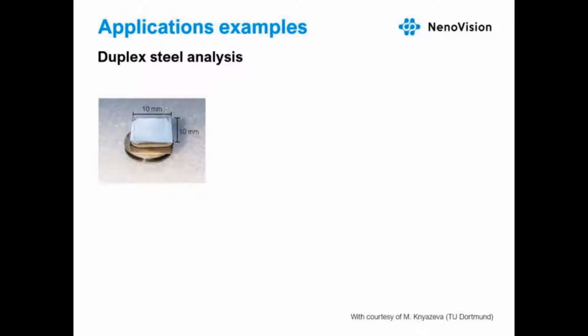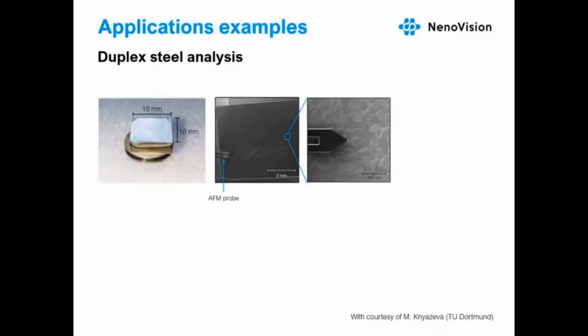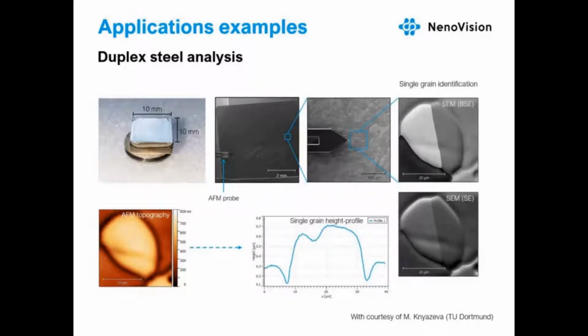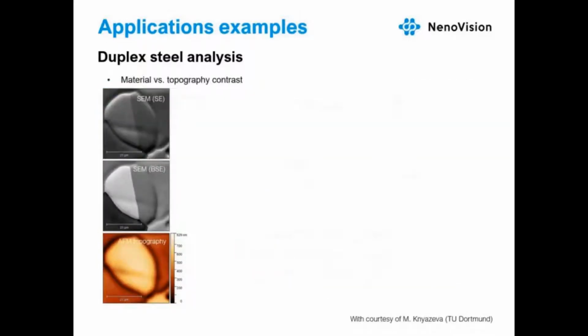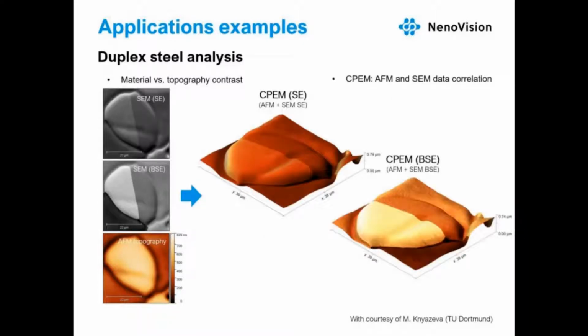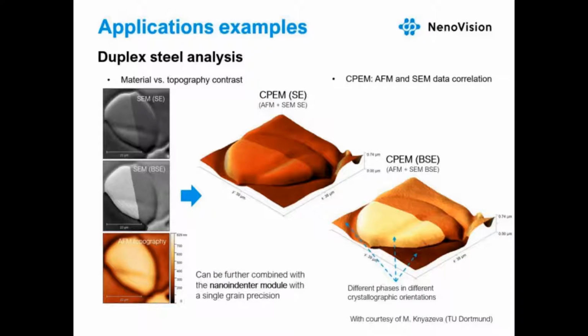So one of the nice examples of the AFM-in-SEM combination benefits is the analysis of duplex steel, where you can identify individual steel grains, precisely measure their topography, and nicely distinguish between two different steel phases. And the result is a fantastic correlation of topography with SE and BSE signals from SEM showing strong contrast of individual metal phases. So correlative CPEM imaging provides an ideal tool for multiple data analysis. And also this application is an ideal candidate for the nano-indenter module, which enables nano-indentation with single grain precision.